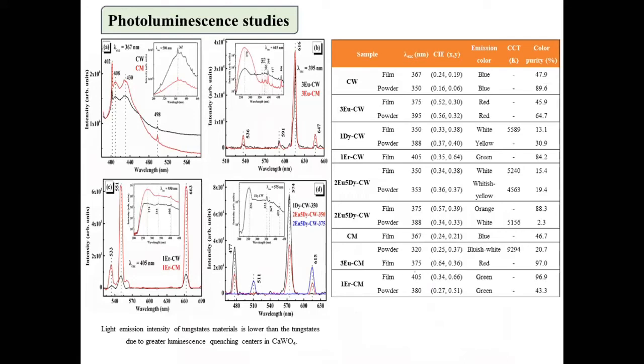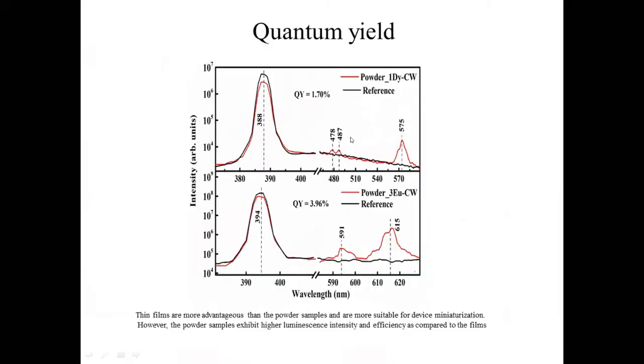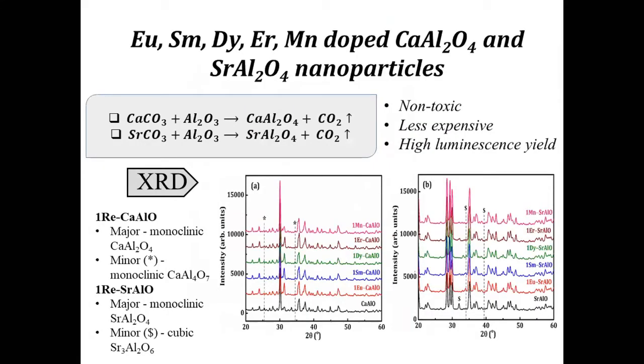And very strong photoluminescence is seen in these doped samples, erbium doped, europium doped, and erbium and dysprosium doped samples. So you can measure the quantum yield, that means the efficiency of luminescence. What is the percentage of light emitted to the total light incident on the sample can be determined from quantum yield studies.